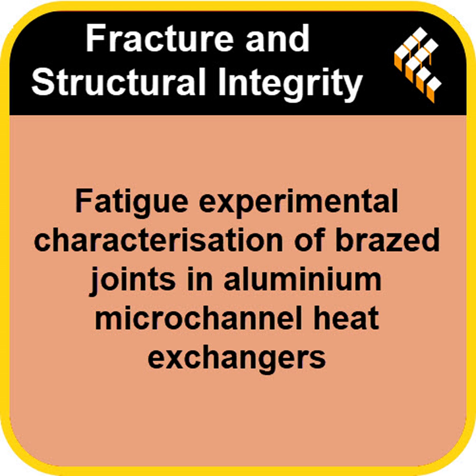So finding traces of these flux elements trapped right at the failure initiation site means? It means these inclusions, which they estimated to be around 75 to 80 micrometers in size. It's actually quite large on a microstructural scale. Yeah, that's not tiny. These are essentially manufacturing defects, remnants of the flux that didn't get fully consumed or displaced during the brazing process and got trapped near the surface in that critical high-stress zone. It's like microscopic chemical contamination left over from the joining process itself. Exactly. It's not just the stress concentration from the geometry, it's these pre-existing flaws, this trapped debris.